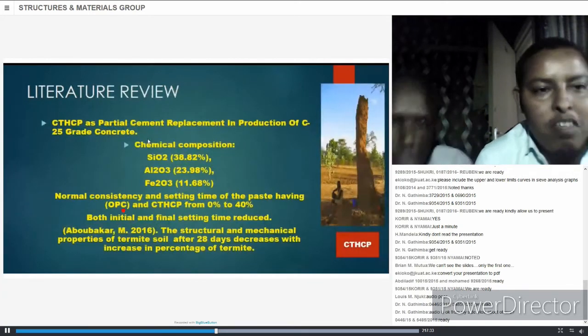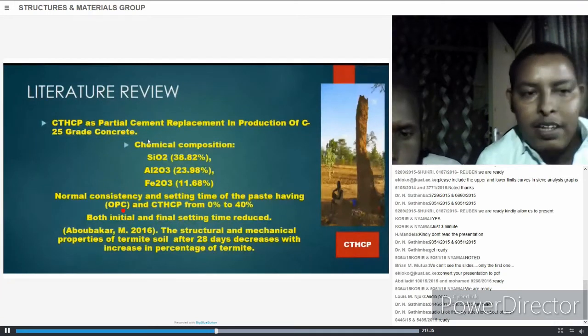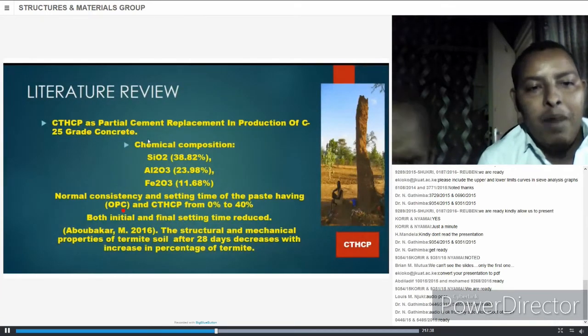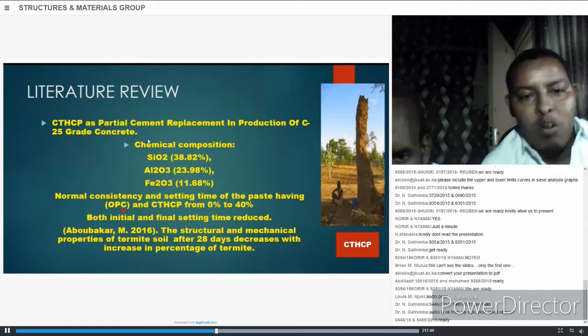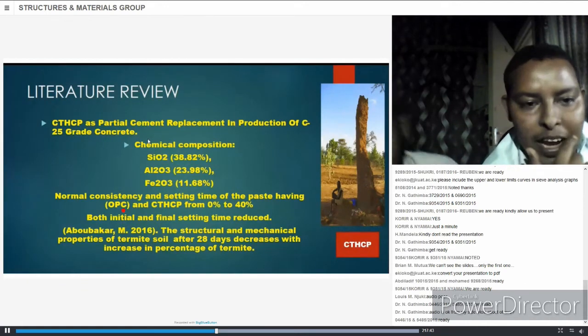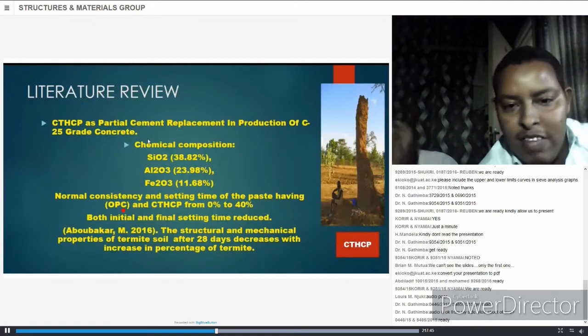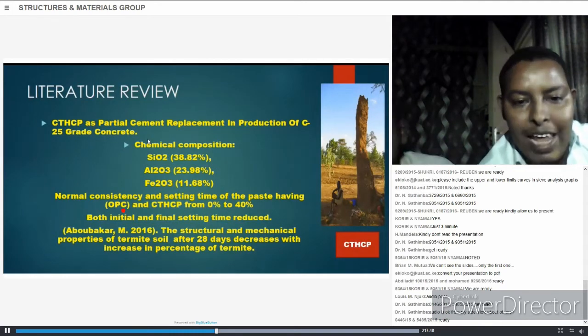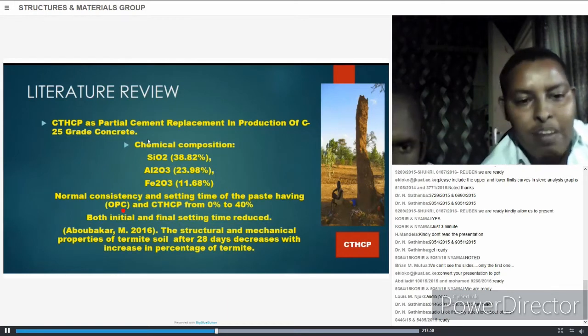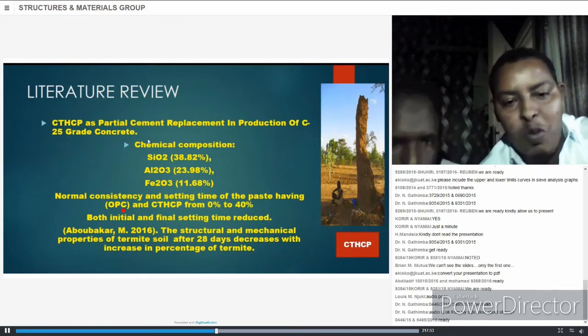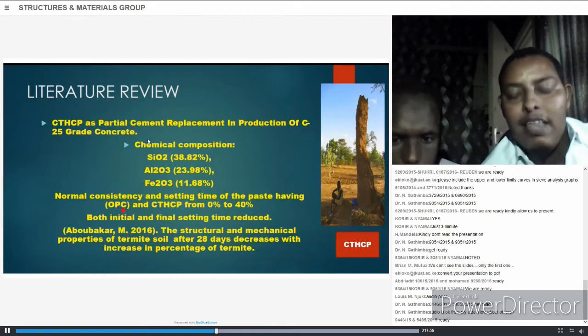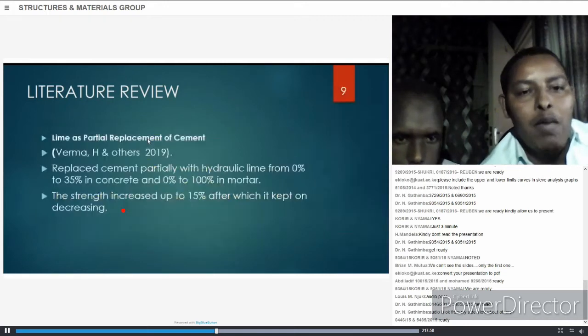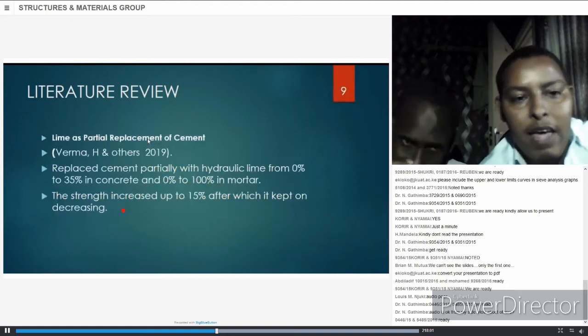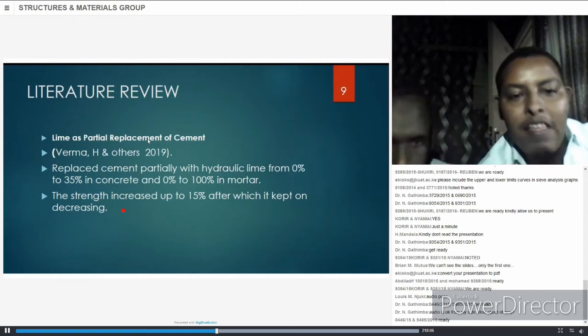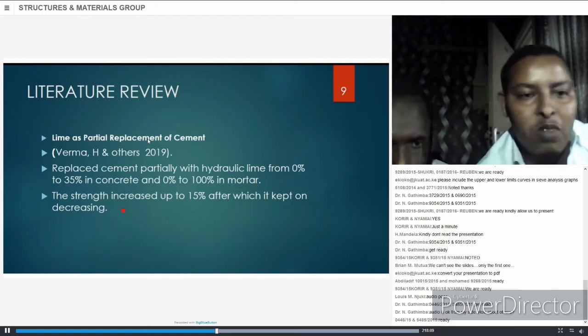Reviews that are relevant to this include someone who did CTHCP, termite hill clay powder partial replacement. They realized the composition includes silicon oxide, aluminum oxide, and iron oxide. They tested for normal consistency and setting time from 0 to 40%, and they realized both initial and final setting time reduced. Someone else, Abubakar, did the structural and mechanical properties of termite soil after 28 days and realized the compressive strength was reduced. Lime was also done as partial replacement of cement by these guys. They replaced from 0 to 35% in concrete and 0 to 100% in mortar. The strength increased up to 15%, after which it kept on decreasing.